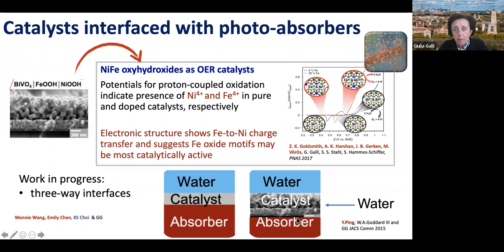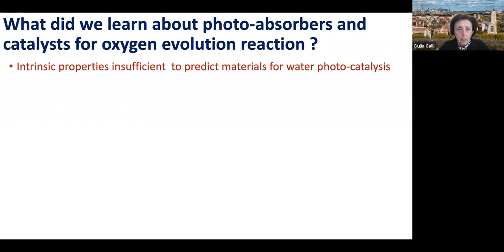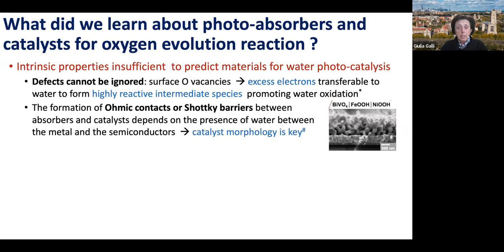So what did we learn by doing all this? Well, first of all, we learned that the intrinsic properties of any material are totally insufficient to predict materials for water photocatalysis. You cannot ignore defects. I showed you an example of vacancies and excess electrons that are so critical to determining what's going on at the interface. And I didn't show you, but we did a study of this: if you want to understand whether you have ohmic contact or Schottky barriers between the catalyst and the photoabsorber, you also need to worry about the morphology. So the intrinsic properties of the materials are absolutely not enough.